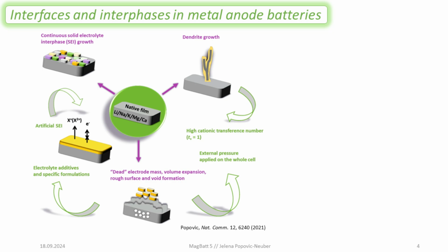And so how do we deal with these two biggest problems? Well, we try to build artificial SEIs. We have already heard a little bit about it. And we try to tune maybe cationic transference number in order not to have this kind of dendrite growth. What we end up with at the end is this dead electrode mass, volume expansion, rough surfaces, and void formation that are in a way non-avoidable in these kind of materials. So I don't think that we have very direct solutions for these kind of problems. So we have to even figure out if we can describe them properly in the next years.